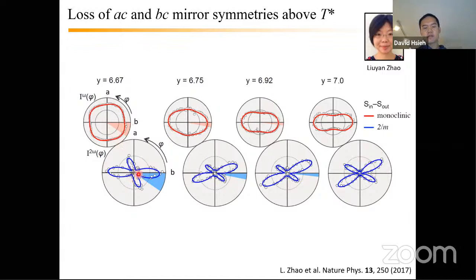And I'm marking here with this red and blue wedge just how much it's offset from this high symmetry axis. And so as you start to dope towards the end member, it starts to heal and go back to what you'd expect of mmm, but certainly as you're far away from it, as there's more disorder in the system, there's this departure, okay? And the reasons for this are currently still not very clear. There could be some subtle crystallographic distortion that just simply wasn't resolved with the available diffraction techniques. But I will say that we can refine these types of patterns under a lower symmetry group, namely this monoclinic 2/m point group.